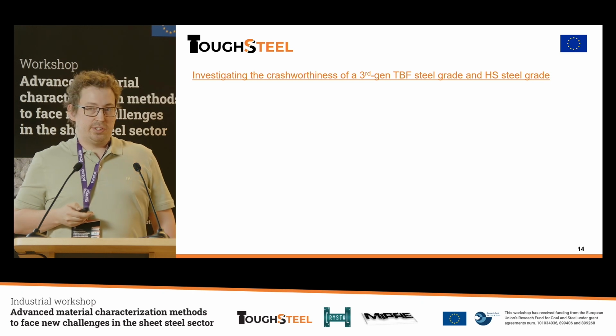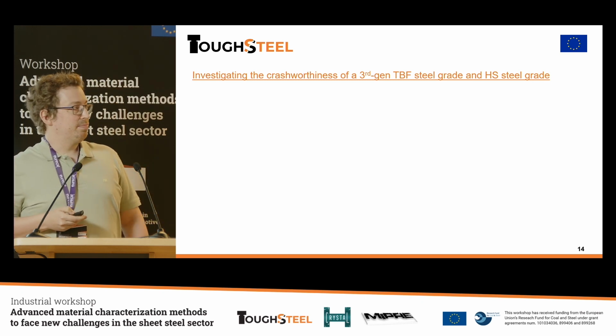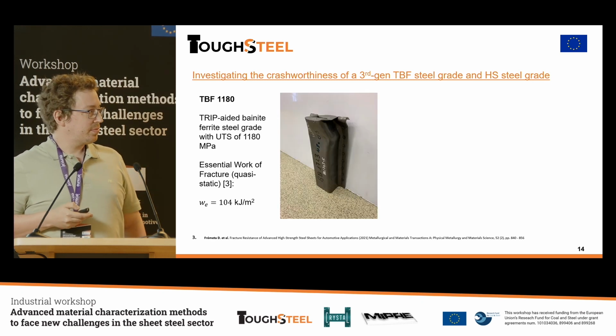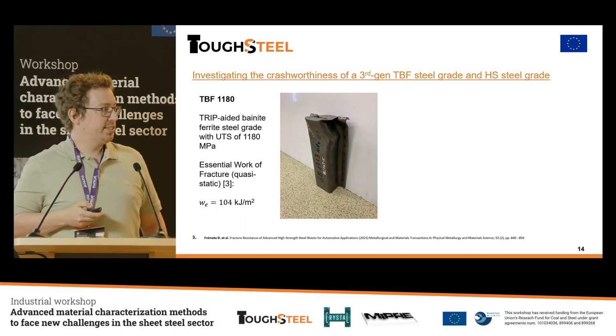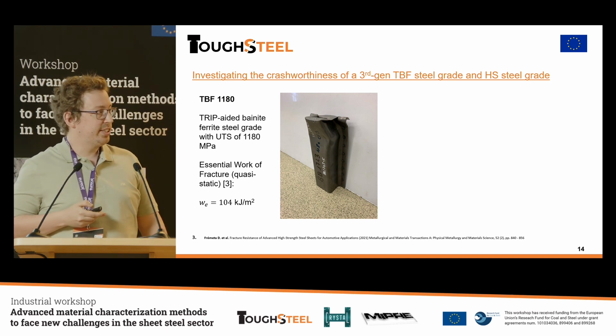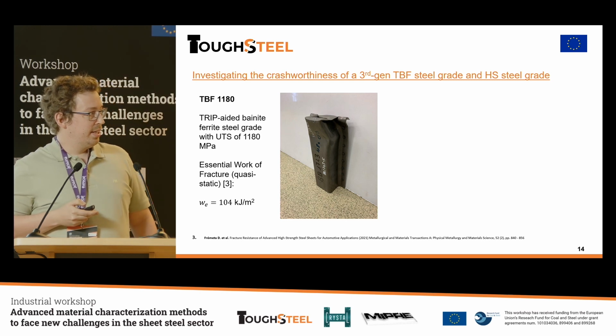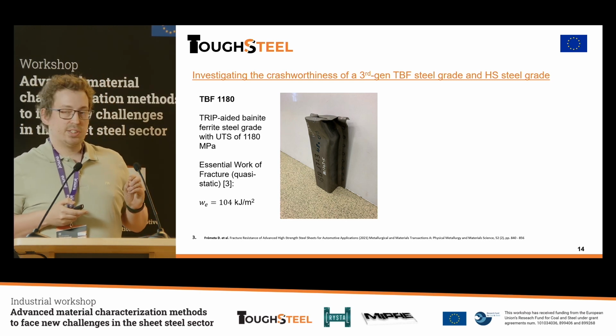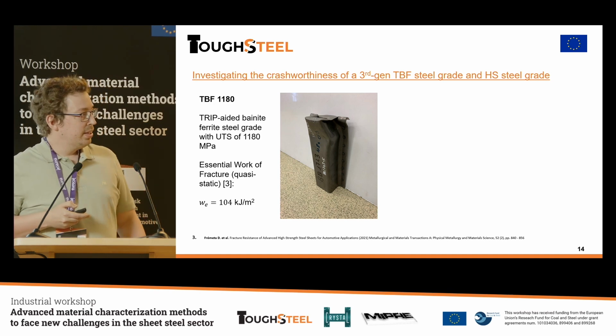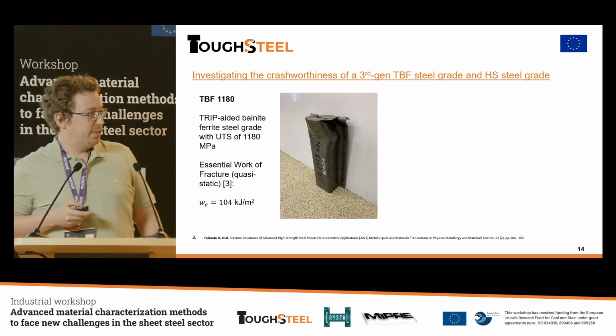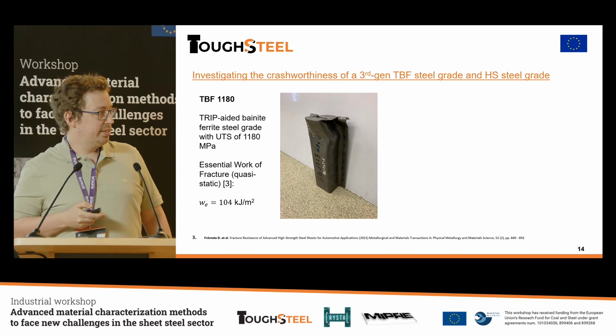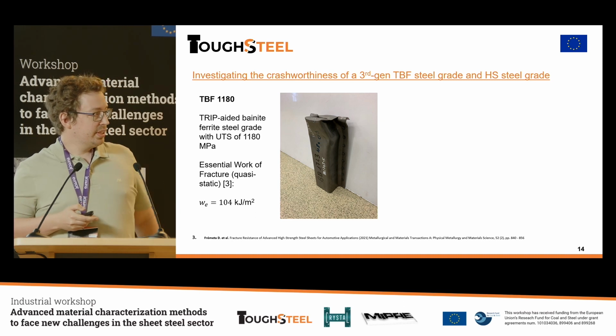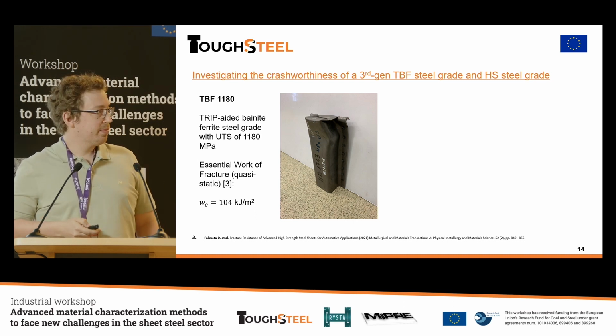So basically, we decided to investigate this with a third generation TRIP-aided bainitic ferrite steel grade with an ultimate tensile strength of 1180 megapascals. And the sheet thickness is 1.4 millimeters here. And I found the essential work of fracture value from Frómeta's paper here, 104 kilojoules per square meter.